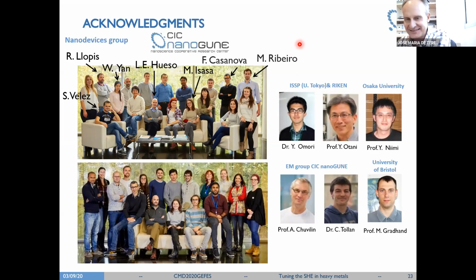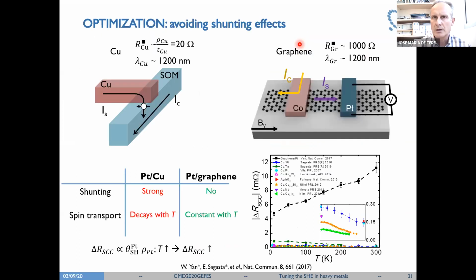Okay, can you hear me? Yes. So first, congratulations for the talk. Very nice work. So the effect you observe is very similar to what was observed in the past with the anomalous Hall effect, that the effect was larger when the resistivity of the material was larger. But of course, you pay some cost, because then the electrical noise is larger, because the thermal noise is larger, because the resistivity is larger. So my question is, if you observe the same effect with the spin Hall effect, that when the resistivity is higher, you have a larger effect, but you have higher noise? Because I have seen in your graphs that the error bar is larger when the spin Hall angle is larger, so when the resistivity is larger. So I guess that you have the same effect, that you have higher electrical noise.